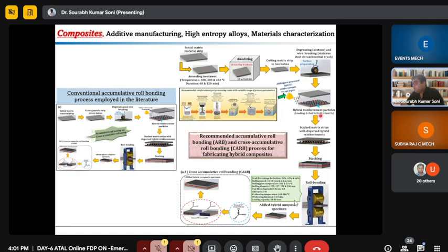And after generating the grooves, we will put the reinforcement material within the two matrix plates, and then after stacking, we will do the rolling operation, either in hot condition or in cold condition. It's totally dependent upon the matrix and reinforcement material. Then we will get a very good ARB processed hybrid composite specimen.